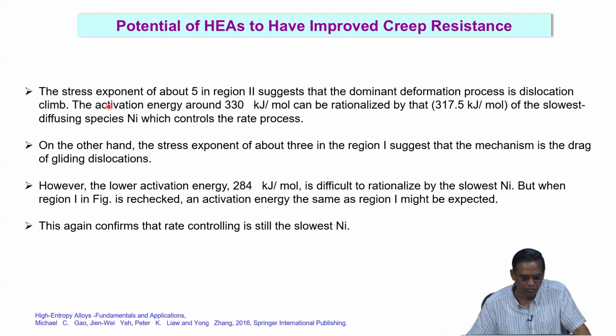The stress exponent of about 5 in region 2 suggests that the dominant deformation process is dislocation climb. The activation energy of around 330 kilojoule per mole can be rationalized by the slowest diffusing species, nickel, which controls the rate process. So this is what I showed: the lattice diffusion of nickel is about 317.5 kilojoule per mole, and you get an activation energy of 330. So you can relate that to nickel diffusion, and the mechanism is basically dislocation climb.